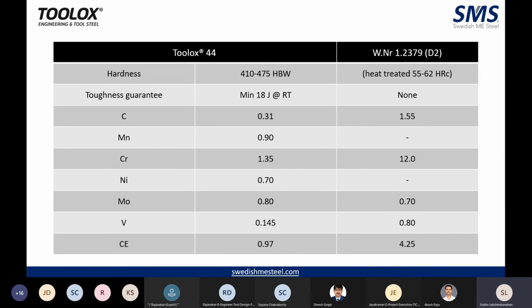This is Toolox 44 compared with D2. As we have already mentioned, for Toolox 44 all the properties are guaranteed. You have a minimum toughness guarantee of 18 joules, where there is none for D2. In the last column, the CE values are 0.97 for Toolox and 4.25 for D2. CE is the carbon equivalent value for the material, and any material with less than 1 is very easy for thermal cutting as well as welding.